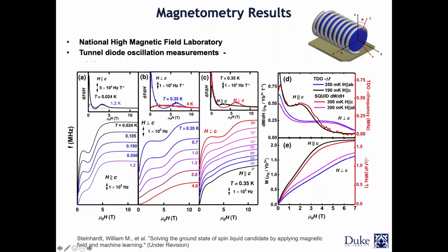What you can see is that these two first show different behavior. So again, it's talking about anisotropy. It's talking about the fact that the spins have a preferred orientation, naturally intrinsic to them. And for example, we can start to move or rotate them to go from H perpendicular to C to H parallel to C, and you can see how it is changing. So this is one thing that we learned from it.